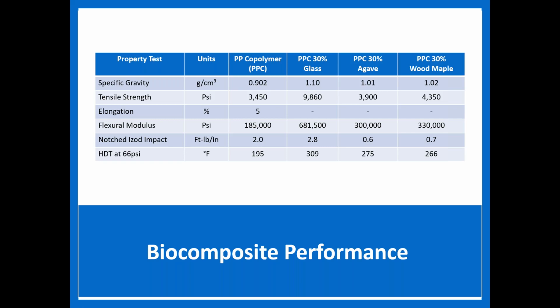So your glass being at almost 10,000 PSI strength, you're getting up to about 4.5 with the filled grades. And then your modulus of 681 KSI for glass, and then 300 versus 330. So again, a little bit of improvement, just not all the way to that of glass. So if you need maybe a little improvement over unfilled and still want the green aspect, maybe this could be something that would get you there.